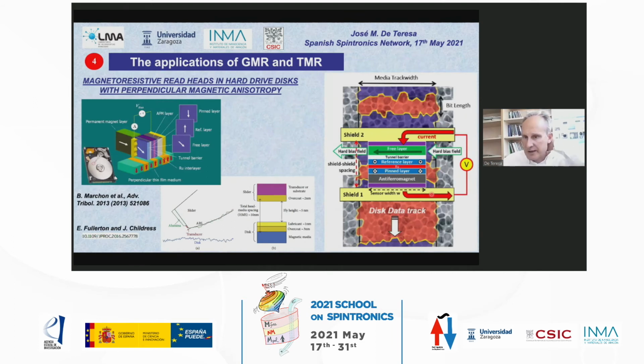Good. So where are we today in this technology? As I mentioned, perpendicular magnetic recording was introduced a few years ago, and as Jairo already mentioned, we have this kind of technology with the read heads, which are brought very close to the magnetic disk, and the sensor is just at the tip of this head. With incredibly small distances, we have the magnetic disk, which has an overcoat of 3 nanometers, lubricant 1 nanometer, fly height only 5 nanometers, overcoat 2 nanometers, and then the magnetoresistive sensor.